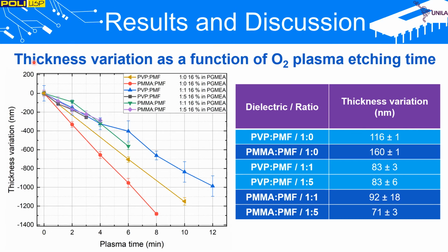Now we discuss the results of thin film thickness variation as a function of O2 plasma etching time. Note that thinner films have fewer data points since they get fully etched after a shorter time compared to thicker ones. Among films without the cross-linking agent, PVP has a lower etching rate compared to PMMA. By adding PMF to PVP at 1:1 mass ratio, there is a decrease of approximately 28% of the etching rate. Further increasing PMF ratio doesn't alter the etching rate. At this ratio, PMMA with PMF showed the highest resistance to O2 plasma etching.